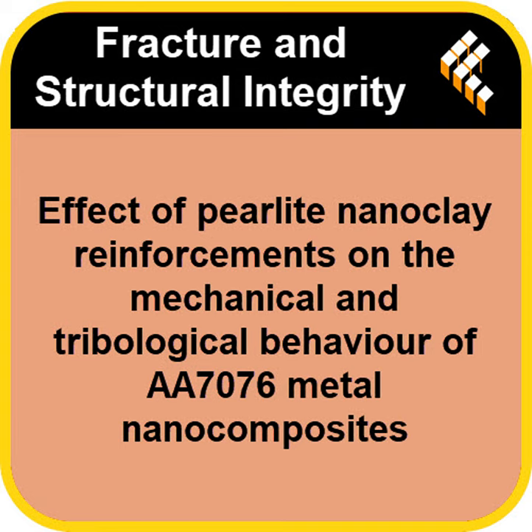But the real test, especially for structural parts like, say, a wing spar, is tensile strength. How much stronger is it before it actually breaks under tension? Right, and this was really the headline finding. The base AA7076, its tensile strength was about 106 megapascals, MPa. The 1.5 weight percent composite achieved over 146 MPa. Okay, do the math. That's a 38% improvement.